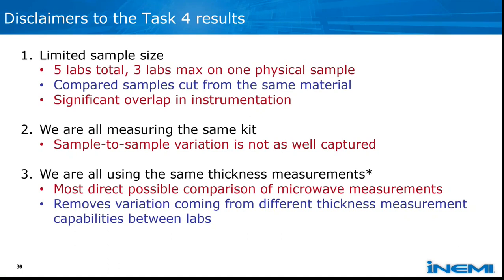Lastly, there's an asterisk next to this one, but we're all using the same thickness measurements. Each lab did more or less make their own thickness measurements as well, but for the point of comparing the microwave side of the measurements, we used the same thickness measurements from Intel so that we could really focus on the microwave side of things. This removes the variation coming from different thickness measurement capabilities of each lab, since that's something we'd already acknowledged was problematic. But like I mentioned before, we did also make those measurements at some of these labs, and I point that out in a later plot.